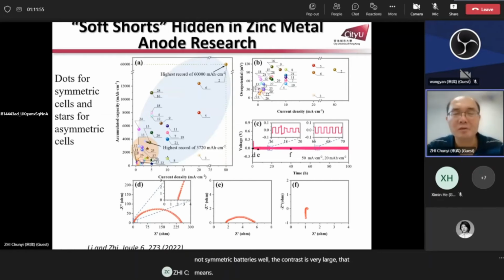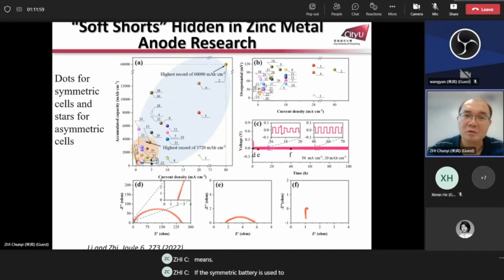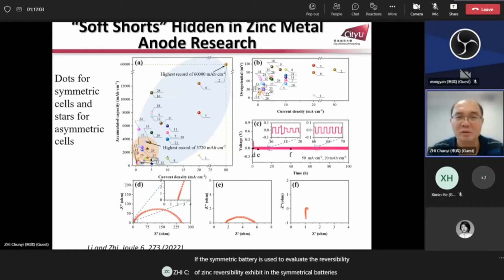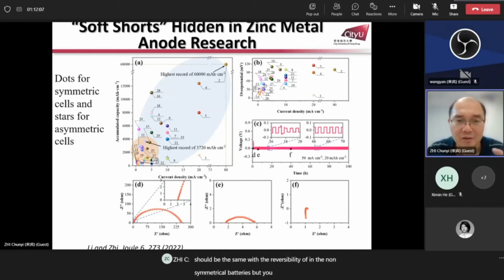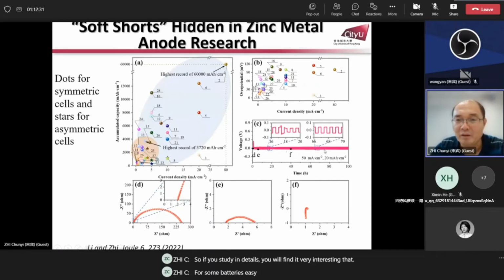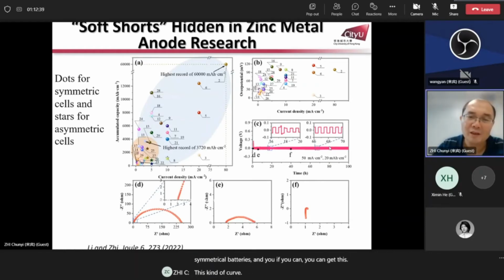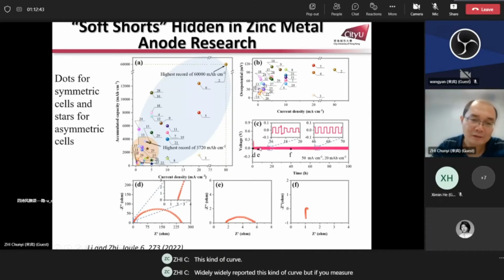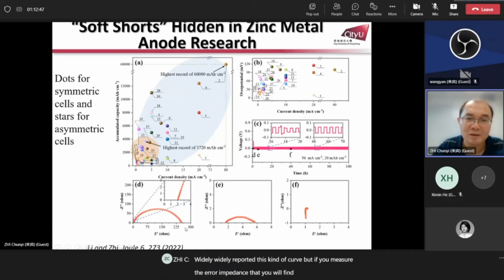That means if the symmetrical battery is used to evaluate the reversibility of zinc, the reversibility exhibited in the symmetrical batteries should be the same as in the non-symmetrical batteries, but you see a large diversity in the data. If you go for overpotential, it is also very diversified, ranging from 90 to very small numbers. So if you study in detail, you will find it very interesting that some batteries exhibit very good cycling stability. Symmetrical batteries, if you can get this kind of curve, widely reported, but if you measure their impedance, you will find that the resistance is getting much smaller. It seems that from here to here something changed.